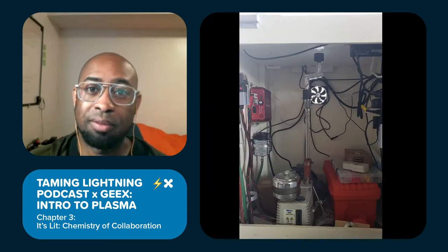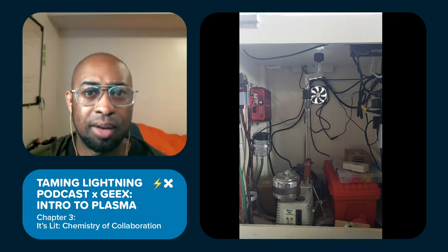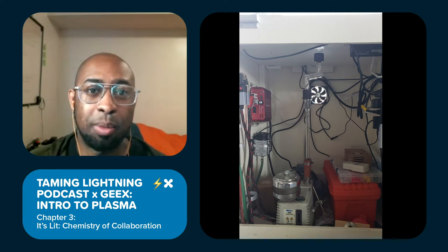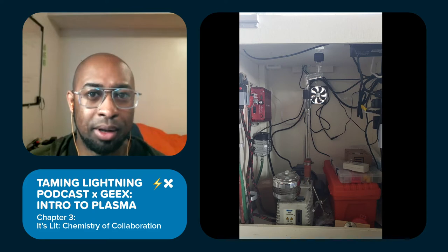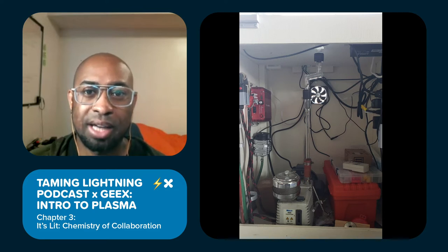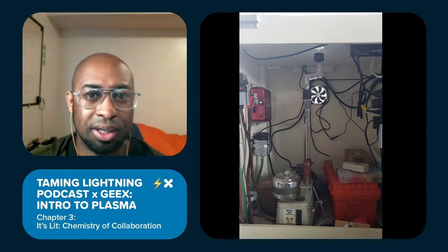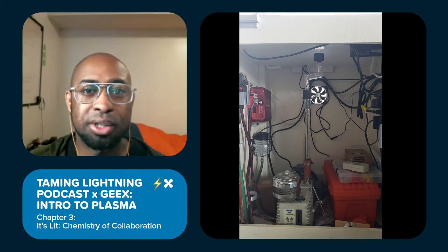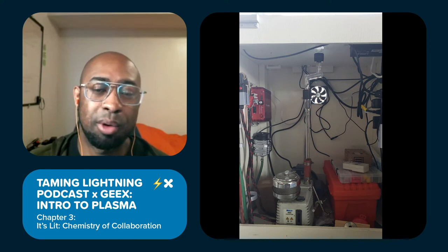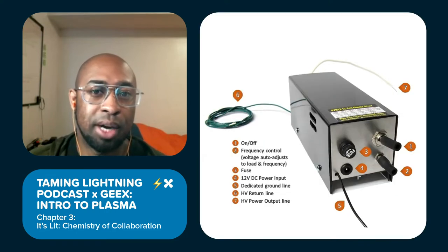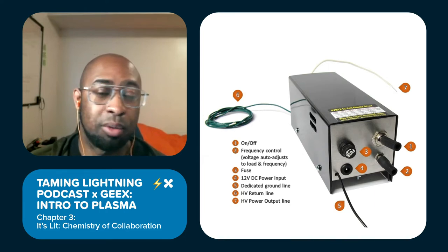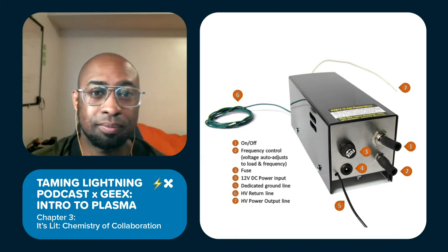Evacuate gases by opening the vacuum to lower pressure and change the effects. Note that if you have added two gases and open up the vacuum, both will come out. And be careful that if you're using other gases or vapors, like halogens, opening the vacuum pump will pump those substances into your workspace. Some transformers can be adjusted in power output to influence behavior. Mixing gas effects and transformer effects will happen simultaneously.